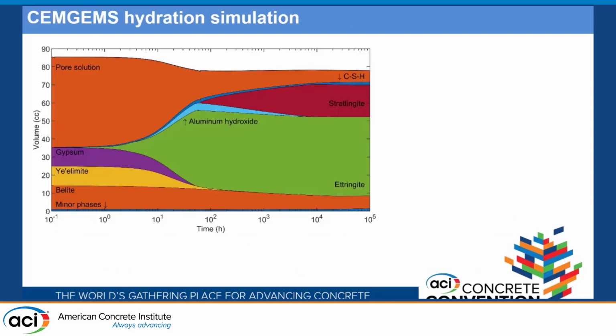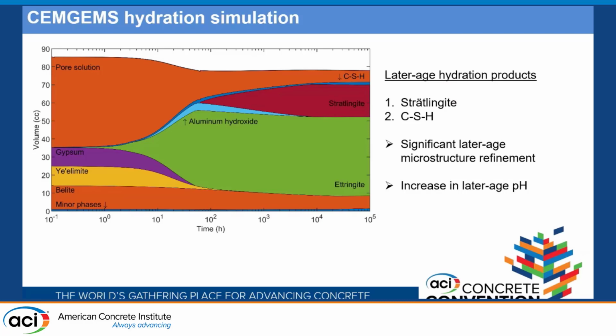Now, I would like to share a simulation that tells you the possible hydration of BCSA cement. And BCSA, as I mentioned earlier, has a late age hydration as well, because it also contains belite, and it hydrates to form a majority of strätlingite and some amount of C-S-H. And based on the results that we have observed, these products seem to have significant late age microstructure refinement for BCSA cement, and also they have an impact in increasing the late age pH, which is extremely important for steel passivation.